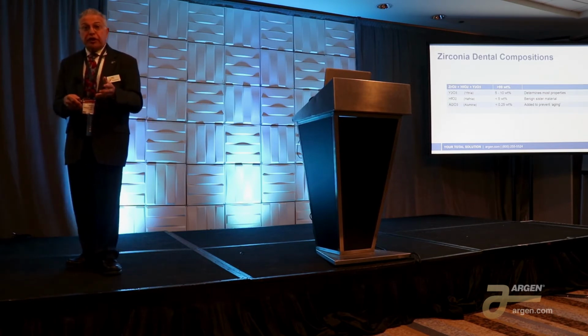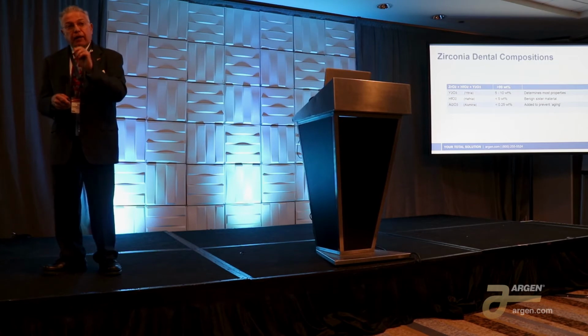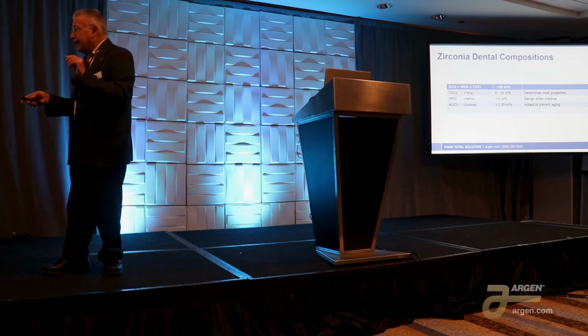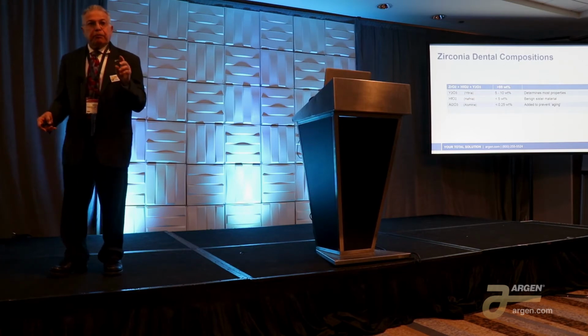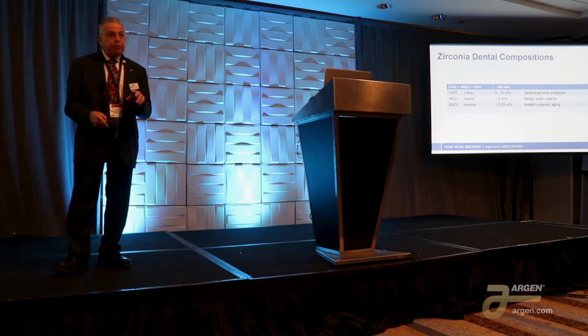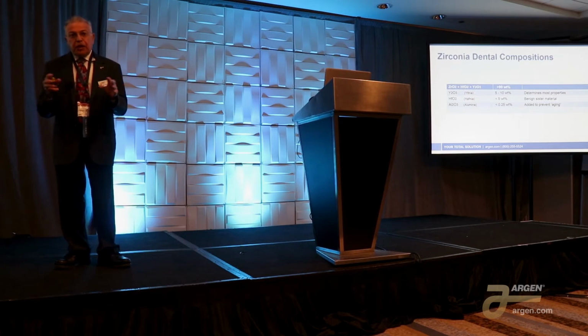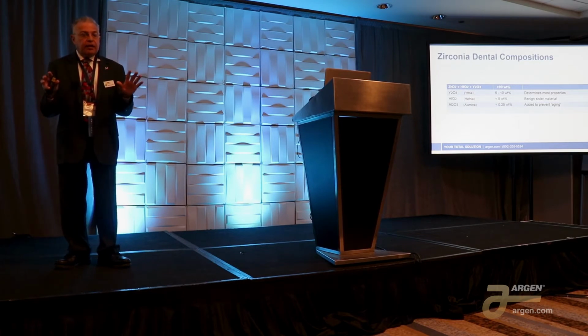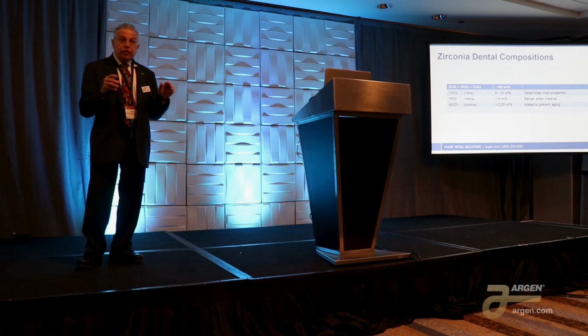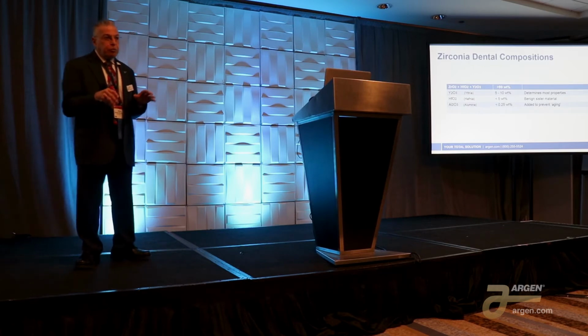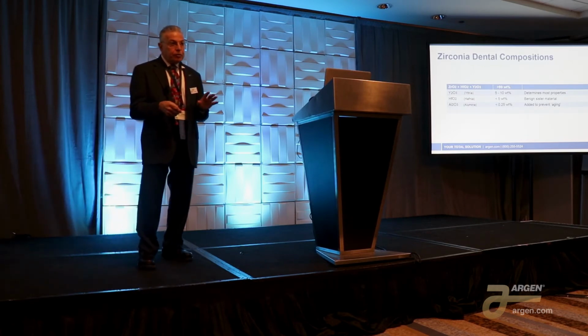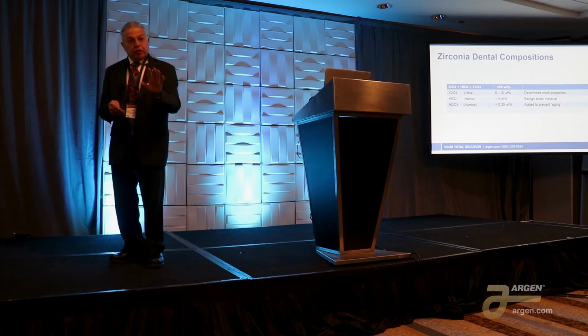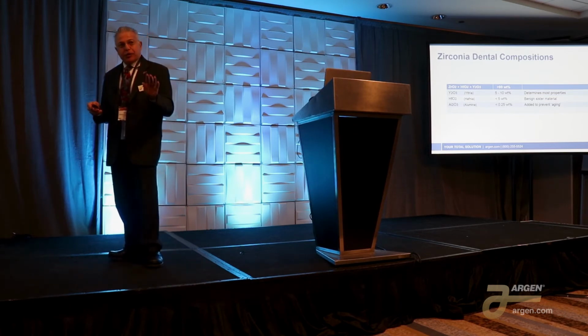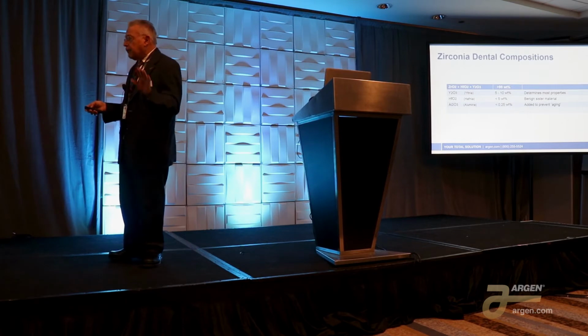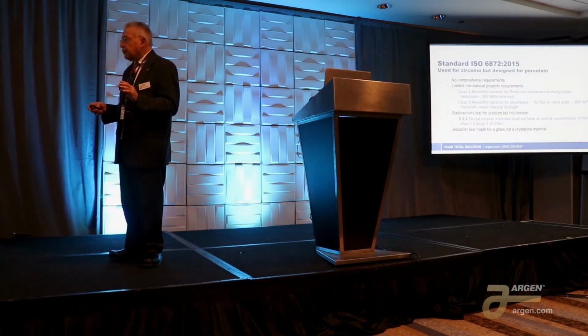So our concern is genuine, and what we found was a way of getting the alumina in the grain boundaries, but reducing the content generally down below 0.1%. And at that point, the material becomes translucent, and that was our starting material. And some of the newer materials, we actually have the alumina down to 0.05%. Very, very small. It's there as an insurance policy to make sure that the aging doesn't happen, but it's there.